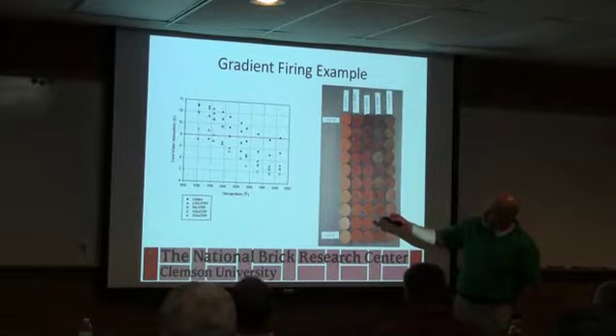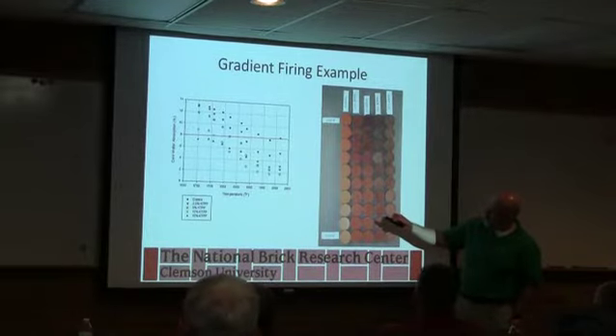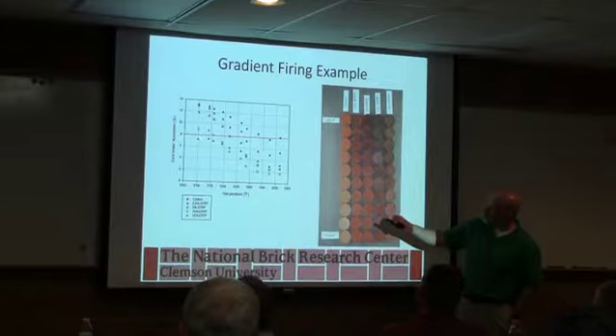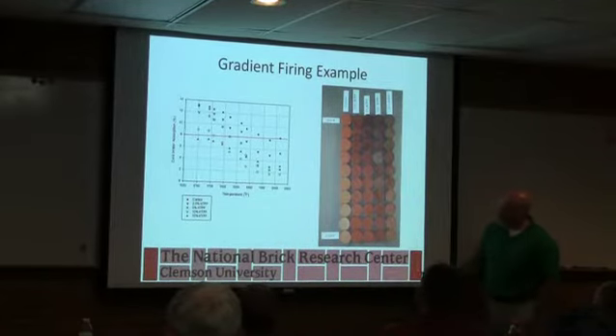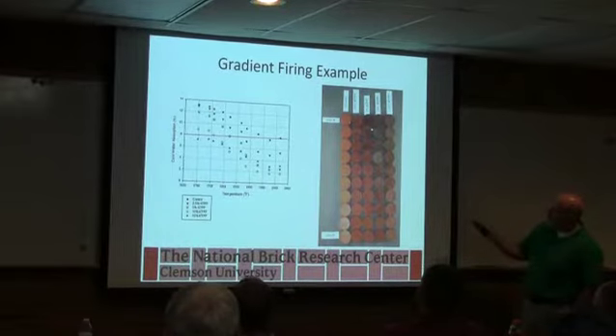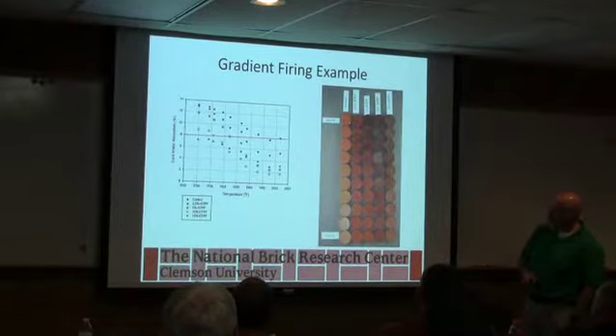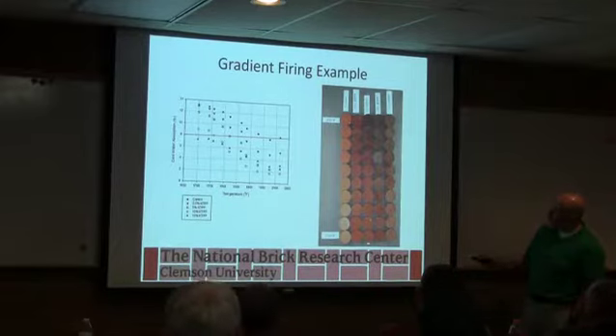We're looking at our absorptions. So we actually increased our absorption somewhere we bloated, but we were trying to stay below 8%. And then as we added more and more of the phosphate, we were able to get lower absorptions, but we didn't get a big reduction in temperature with that particular experiment like we were expecting. And we also kind of played havoc with our colors. So anything beyond this 5%, it started to go kind of brown on us.